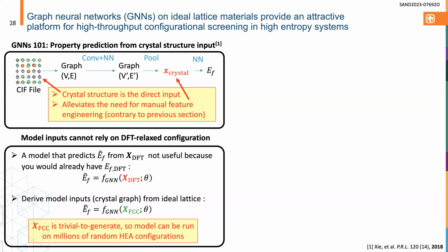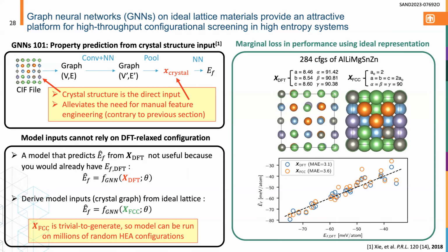So if that's your input to the neural network, it's essentially a useless model because you already have the answer, right? You already have the DFT formation energy. So we need our model inputs to be based on the ideal lattice structure. If you map all your atoms to some idealized FCC representation, you can do the site disordering and screen essentially millions of random HEA configurations, so long as you can predict what the relaxed formation energy should be from that idealized structure. That's exemplified in the next little section here.